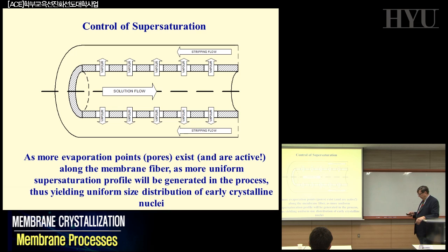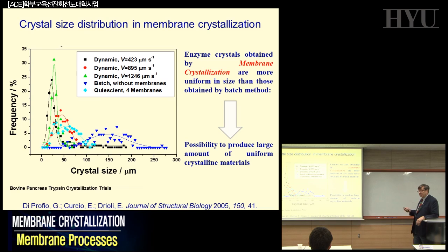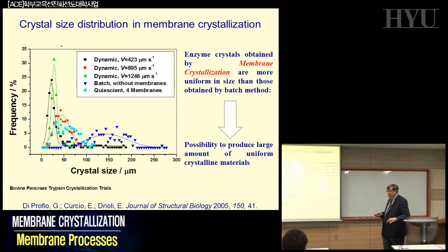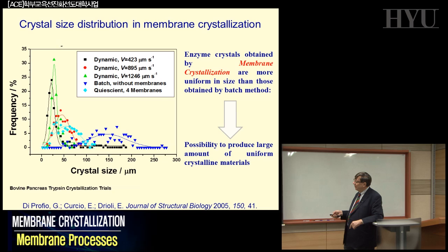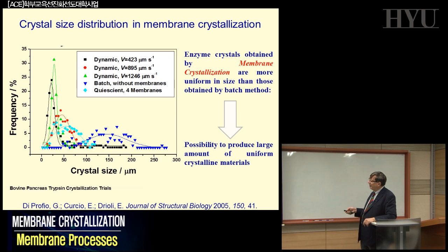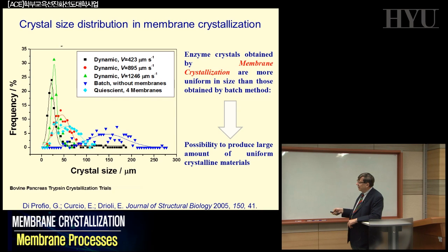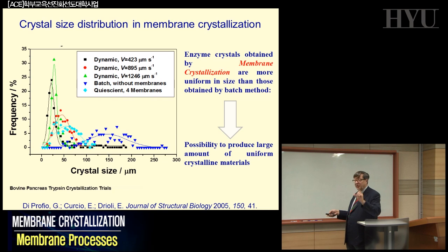And that, in fact, is one of the points that has been very easily demonstrated from the very early stage. If you just study the crystal size distribution using this kind of approach, and you plot the frequency of a certain dimension, in certain habits in your system, as a function of the crystal size, you will see that changing also the linear velocity, but you see here, if you don't have the membranes, that is the typical distribution in a traditional batch with no membranes. When you introduce your membranes, you have this kind of frequency of appearance of a certain geometry in your system compared to the other one.